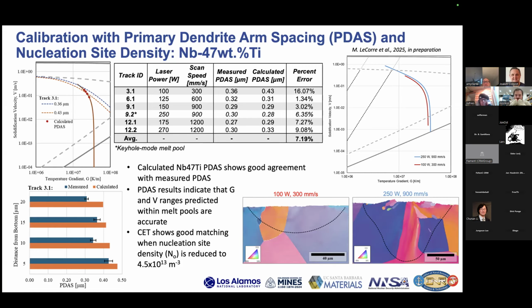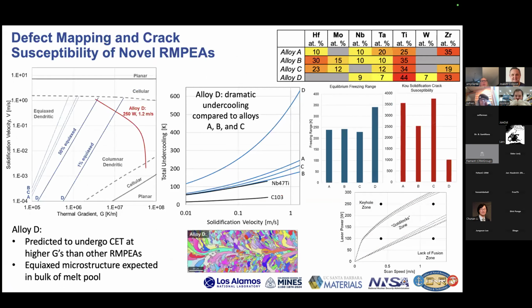And so this is now making some assumptions about nucleation site density. This is kind of a fudge factor in these approaches. And this is sort of bound right now, at least for the moment, with some tri-beam data sets that were generated by Andrew Polonsky, one of Teresa Pollock's former graduate students. We've now moved on from classic refractory alloys to these refractory multi-principal element alloys or refractory high entropy alloys, which is a pretty interesting area to think about.